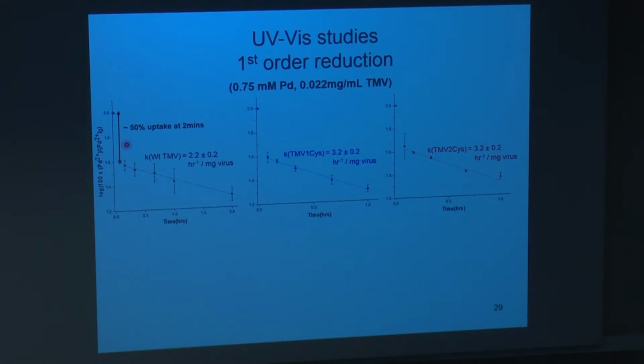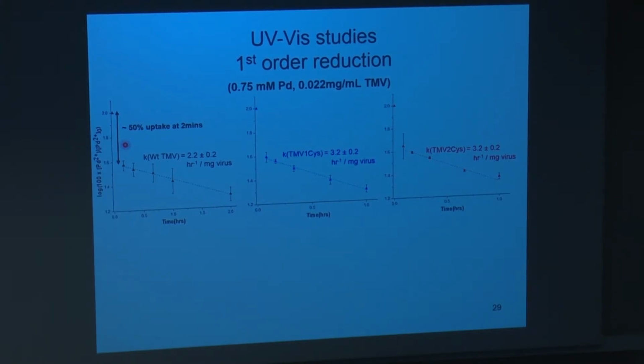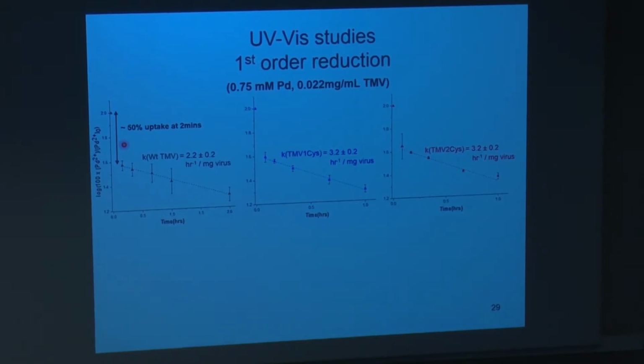And these are the rate constants that we got, 2.2 per hour per milligram of virus, because we try to normalize by the amount of virus we had in there, because the rate constant tended to increase as a linear function of the mass of the virus. And so we showed the wild type TMV, 1 cis TMV, and 2 cis TMV. As you can see, going from wild type to 1 cis, the rate constant was 3.2. However, for 2 cis, it remained at 3.2. And so these are the last two of the genetically engineered wild type TMV.